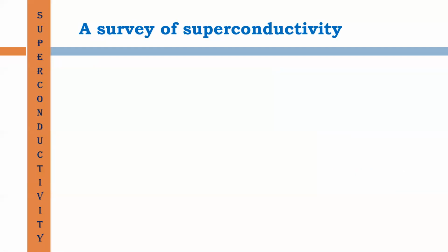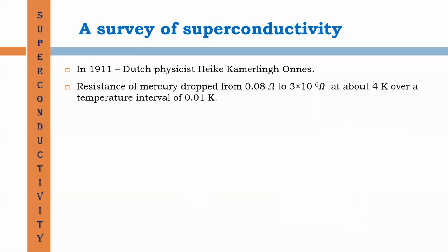Then we discuss the survey of superconductivity. It was observed in 1911 by the Dutch physicist Kamerlingh Onnes. It was observed in mercury. The resistance of mercury dropped from 0.08 ohm to 3 × 10^-6 ohm at about 4 Kelvin over a temperature interval of 0.01 Kelvin.